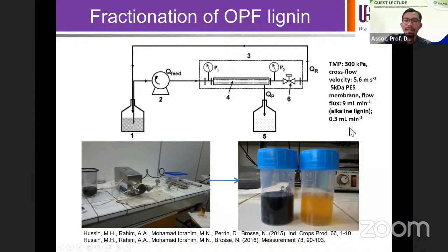So this shows you that before the experiment, you have a black liquor, and after the ultrafiltration, you will see that the color of the black liquor is slightly pale, which indicates that you have a lower size of lignin that passes through the membrane.